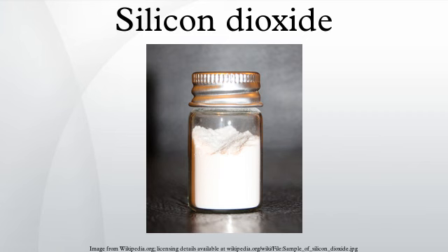As an example, a reaction of sodium oxide and SiO2 can produce sodium orthosilicate, sodium silicate, and glasses, dependent on the proportions of reactants: 2 Na2O + SiO2 → Na4SiO4. Na2O + SiO2 → Na2SiO3. 0.25–0.8 Na2O + SiO2 → a glass. Examples of such glasses have commercial significance, for example soda-lime glass, borosilicate glass, lead glass. In these glasses, silica is termed the network former or lattice former.